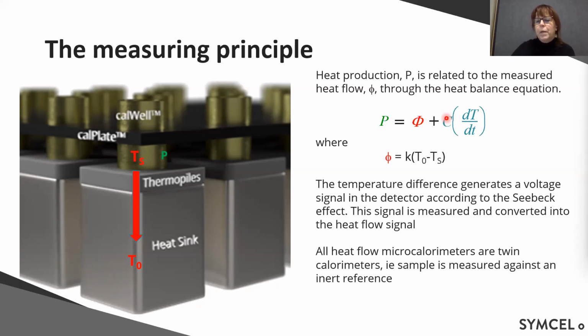It's very small compared to the whole reaction that you're measuring if it's slow reactions. Even if it's fast reactions, we let all heat flow out. So this will come out eventually as well, because we want to channel the heat out of the system. The heat flow we are measuring is directly related to the temperature difference between the surrounding temperature and the temperature in the sample. So it's a temperature difference over the detector.